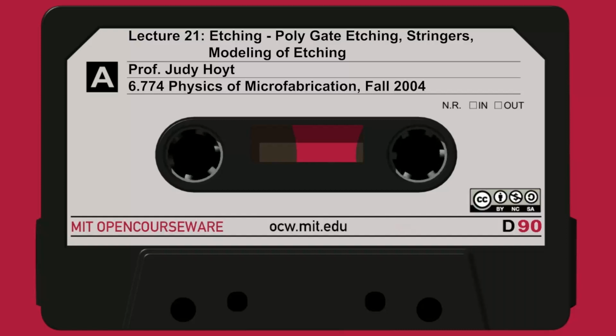A more anisotropic etch, but also not very selective to SiO2, would be a mixture of CF4 and hydrogen, or CHF3, some of these freon types. You can mix CF4 with oxygen. I think we showed last time an example of the chemistry of this. It's isotropic, generally, reasonably isotropic, but it's more selective to SiO2. Again, a lot of times you're etching poly on top of oxide or some dielectric, and so the selectivity of the etch, of the polysilicon etch to the SiO2 is very important.